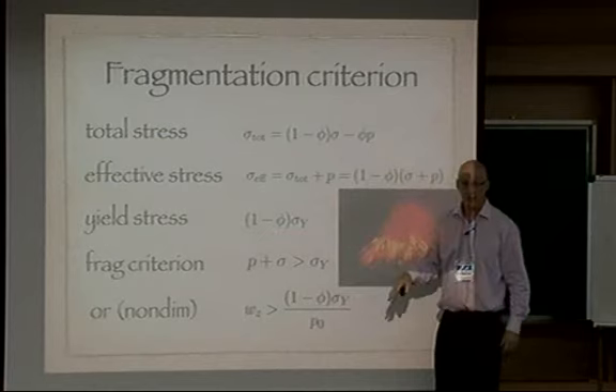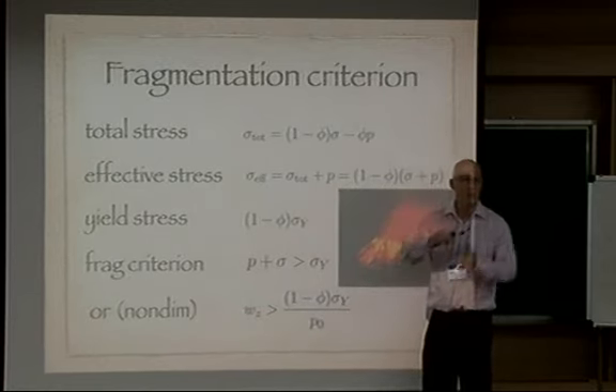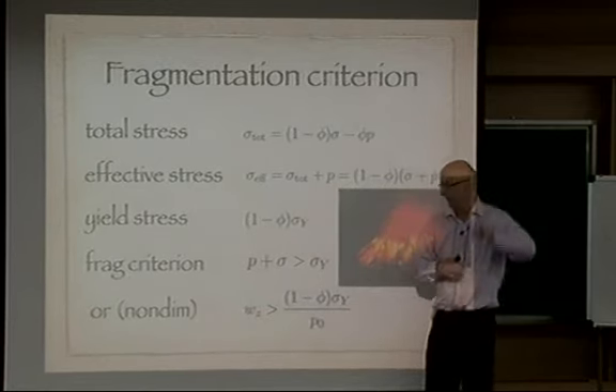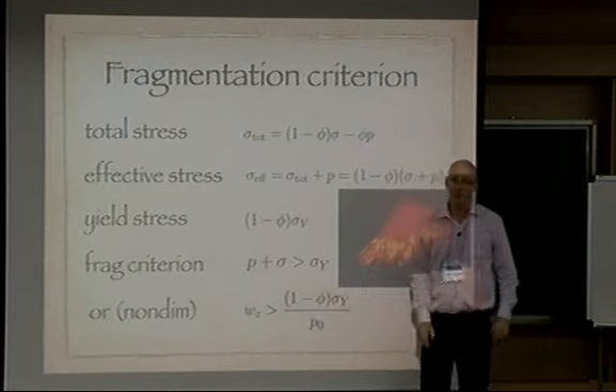If we go to the non-dimensionalization, which we've been talking about, that becomes, we're interested in when W subscript Z, dW dz, is larger than this rescaled tensile strength, rescaled on P0, where P0 is the initial overpressure, 10 MPa, and 1 minus phi is 1 minus porosity.